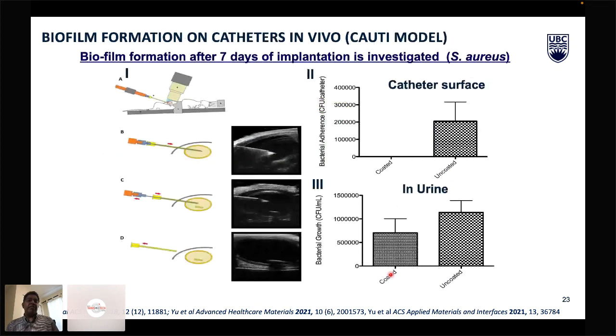And further, although this is good in vitro, we looked at whether it is going to be effective in vivo. That is what we showed utilizing Dr. Lang's model. Dr. Lang helped us to evaluate this using a mouse model of urinary catheter infection. You can see that the coated surface is able to prevent bacterial adhesion remarkably well, but since this coating does not have any antimicrobial agent, it is not able to kill the bacteria in the urine. This work shows that an anti-fouling surface could effectively prevent biofilm formation on the surface.